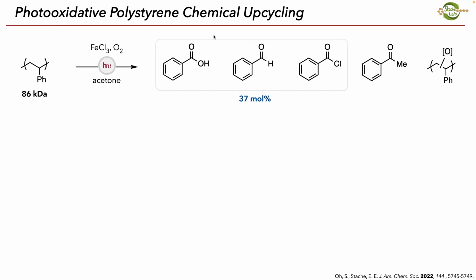And so of these first three, benzoic acid, benzaldehyde, benzoyl chloride, he detected 37 mole%, which means that 37% of these different repeat units were converted into this product. So 37% of the polystyrene, most of it being benzoic acid, and then a small amount of acetophenone, and the remainder of the sample being these oxidized styrene oligomers.